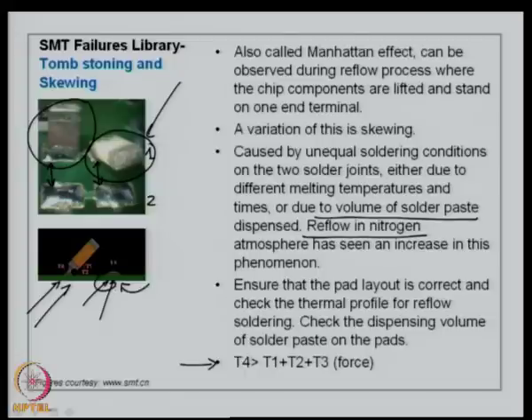Now, once that is done from the design stage, the next thing that you have to check is the thermal profile for the reflow soldering process. And make sure that the melting temperatures are attained in a fairly quick time without too much of exposure to the component. And then you also have to look at the component density on the PCB as a whole. So, thermal profiling becomes very important to avoid these kinds of defects, and also you need to understand the components of the solder paste material.